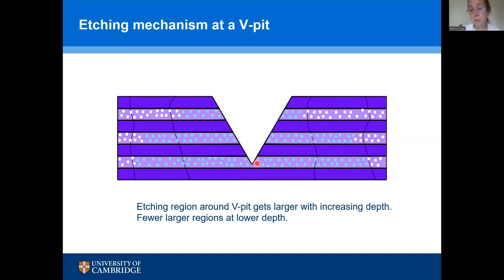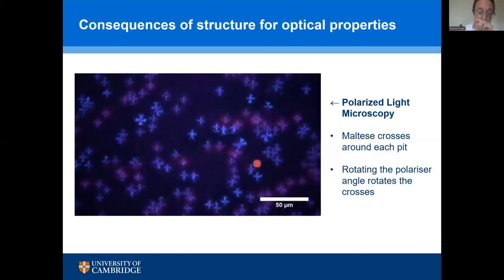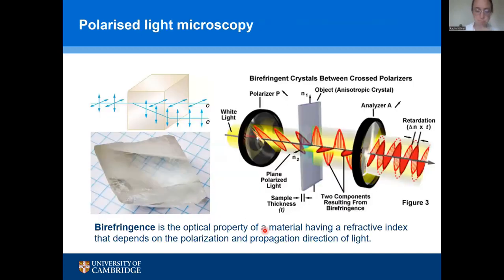Now, that's a nice bit of microscopy. It's a nice science story, but it also revealed some things to us that were surprising about the optical properties of this material. What I'm showing you now is a polarized light microscopy image of this sample with these great big pits in. And looking in polarized light microscopy, we can see these Maltese cross structures, in blue and purple, each with a dark center. If we rotate the angle of our polarized light, we can cause those crosses to rotate in our field of view. Now, what are we doing here?